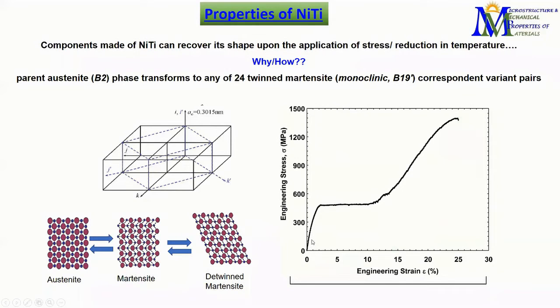And you can see that we have an elastic limit and then there is a plateau strain, which actually signifies that this entire strain will be recovered. And then there is a martensitic deformation. Okay, we have a fully martensite structure at this point, and afterwards there will be an elastic deformation and plastic deformation of martensite till it fails. So this is what we are going to get if we are deforming a nickel titanium based, or for that